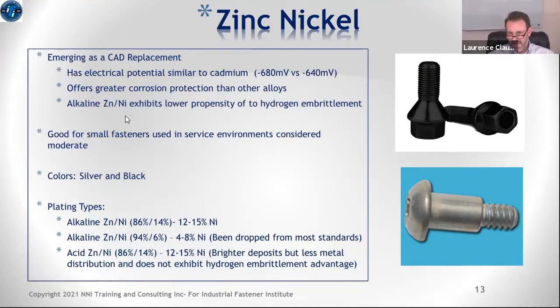At the very bottom of the slide, if you just turn your attention there, you can see that zinc nickel can actually be applied in several different fashions. You'll see there are some titles there: alkaline zinc nickel and acid zinc nickel. Alkaline and acid refer to the electrolyte bath, the plating bath that the plating is done in. Acid basically means that the pH of the bath is on the acidic side, and if it's alkaline, the pH of the bath is on the alkaline side.